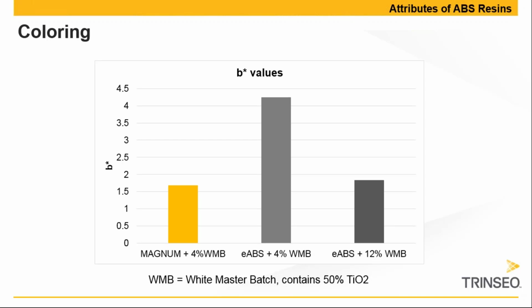And on this graph, I represent here the color as a B star value on the vertical axis. And the higher the B star value, the more yellow the appearance is. And what we've done here is we have added 4% of a white master batch to Magnum and also to the Emulsion ABS. And that white master batch contained 50% of titanium dioxide. And at the same white master batch dosing levels, you can see that the Emulsion ABS is 2.5 units higher in B star value. So clearly more yellow. And it needs up to a factor 3 more of white master batch dosing to bring the Emulsion ABS to the level of Magnum.